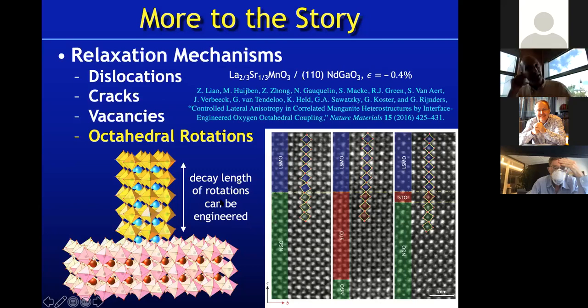So here's a beautiful example from Rijnders' group in Twente, where they've put lanthanum strontium manganite, a nice quantum material, on top of neodymium gallate. So this is biaxial compression, if we just think of things as pseudo-cubic, of about 0.4%. But in mapping out the octahedral rotations, you can see in these nice colors clearly where the interface is between the lanthanum strontium manganite and the neodymium gallate. The neodymium gallate has these clear octahedral rotations, and you can see that those rotations are inherited by the film, but it makes its way toward a steady state, and that decay length of those rotations is a few unit cells. It's several nanometers.